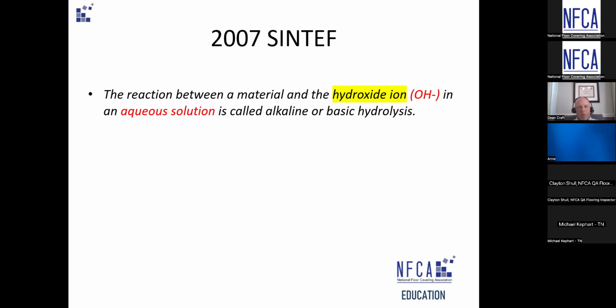What is happening when this pH level rises is called alkaline or basic hydrolysis. That is the adhesive or the flooring backing being put into contact with these hydroxide ions, the OH, in the solution and breaking down. So to say pH is not important skips what actually is the chemical reaction that's causing that material to go back to a goo, or the backing to degrade. It's a high alkaline environment based on a solution.